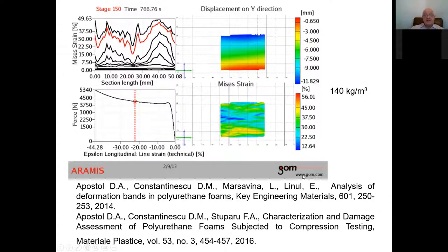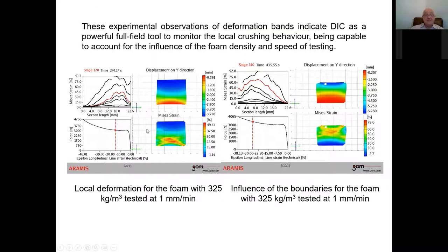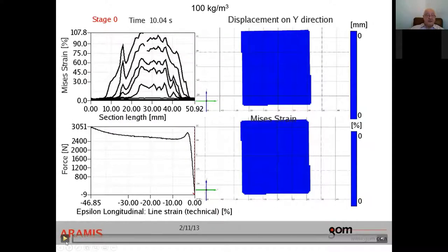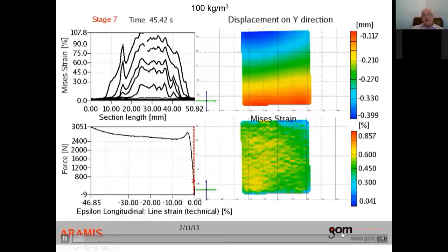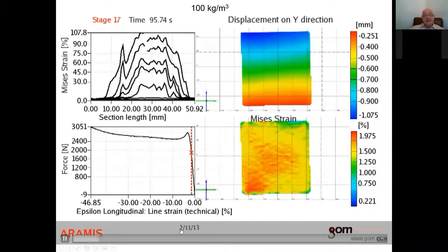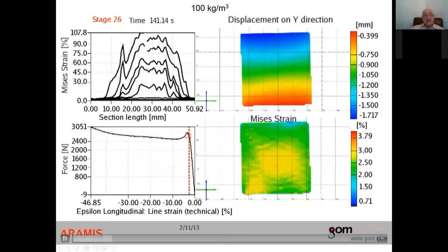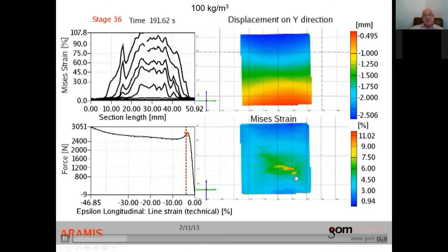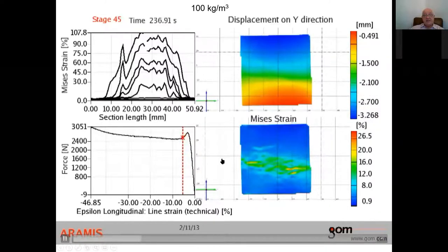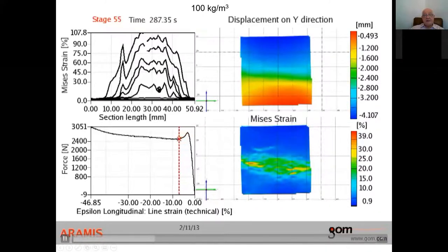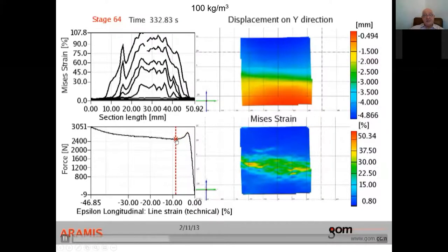We published some of these results, and here, as I mentioned, things are not so simple, because if you change the density, you may have some other distribution of the deformation bands, as you can see here, a kind of X distribution. I would like to show you what is going on. This is a short movie, so the point moves on the characteristic curve at different points. What you see is this kind of localization of the strain. At a certain moment, one of these curves becomes red as you reach the point, as you see here, it was the first one.